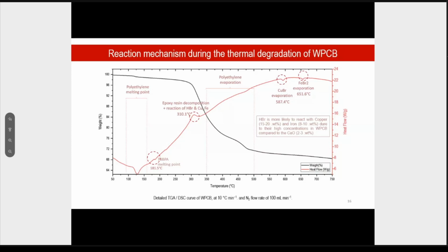So here we can return to our first graph, presented for the thermal degradation of waste printed circuit board. By studying individually the thermal decomposition of the different components, and with the synthetic mixture, we can explain the thermal degradation of waste printed circuit board. As we can see, it first starts with the melting point of polyethylene at low temperature, followed by the melting of tetrabromobisphenol A.